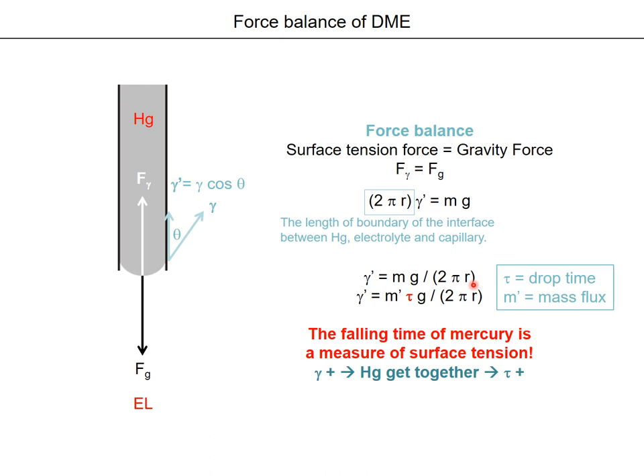In a fixed experimental setup, r is constant, 2 pi is constant, and of course gravity is constant. The mass is split into two terms. The first one is mass flux, and we could control the mass flux value to be constant. Then there is tau, which is the drop time. That is to say, after you recognize that M prime, or mass flux, is constant, then you could know that gamma prime could be calculated by the falling time of mercury. That is to say, the falling time of mercury is a measure of surface tension.